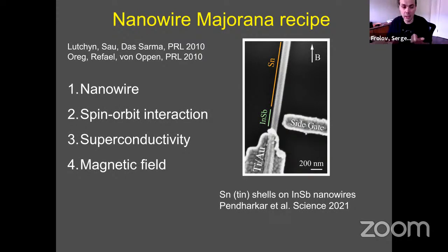Now you have a problem, because superconductivity likes to pair electrons in a spin singlet, and the magnetic field, of course, likes to flip all the spins in the same direction, in a triplet. So you have a problem. And this is where spin orbit coupling, ingredient number two on the screen, comes to help. Because with spin orbit coupling, you couple singlet and triplet, you make peace between magnetic field and superconductivity, allowing it to survive to the regime where you can find Majorana. So that's the idea, that's the recipe. The numbers make a lot of sense, at least at the zeroth, first level. Maybe when you get into the nuances of the material science of nanowires, you start getting a little doubt. But it is a very good idea.